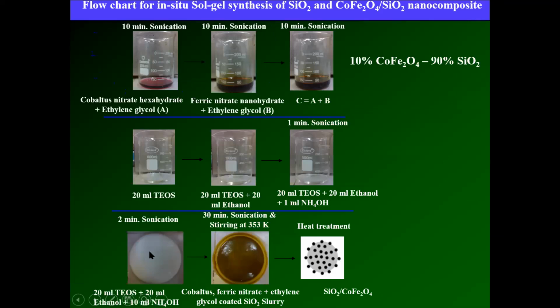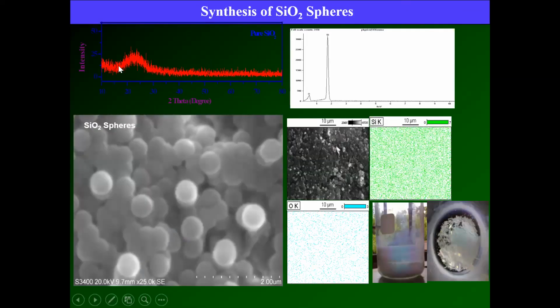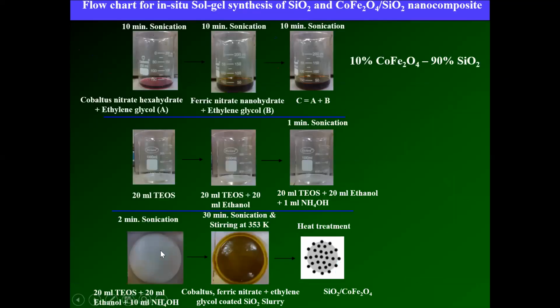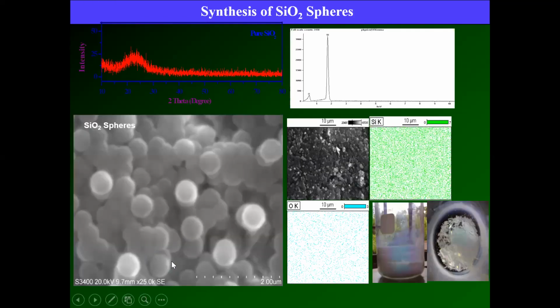Now we try the pure SiO2 first. When you take the XRD, you can see that it is amorphous. So SiO2 is in the amorphous phase. What is the particle shape and microstructure? You can see highly homogeneous spherical particles of SiO2. To confirm it is SiO2, you do the EDX, energy dispersive spectroscopy, to see what elements are inside the sphere. You can see silicon and oxygen only. No other peaks are appearing. So these particles are purely SiO2 and they are in an amorphous, disordered form. These are the elemental analysis and direction. So what we prepared is pure SiO2 with an amorphous phase.